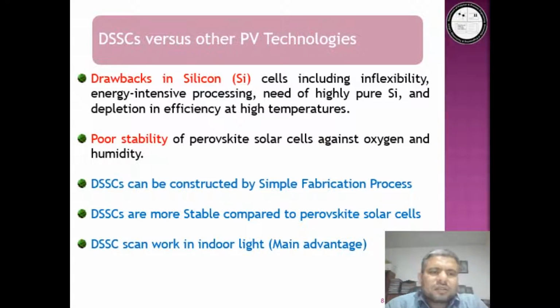Still, the silicon-based solar cells are most demanding in the market of photovoltaic cells due to high efficiency of approximately 15 to 20%. However, their energy-intensive processing, rigidity, reduction in the efficiency at higher temperatures, and requirement of extremely pure silicon are the prominent concerns in silicon solar cells. The presence of these concerns stimulated the researchers to investigate the novel organic materials for photovoltaic applications.